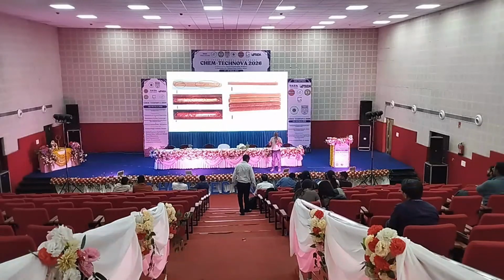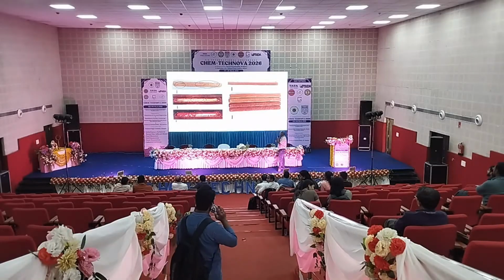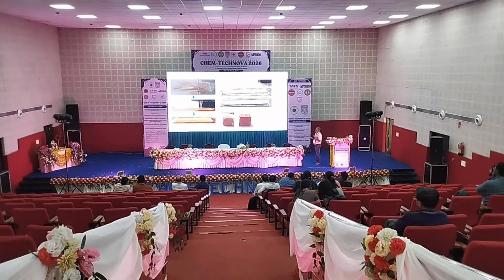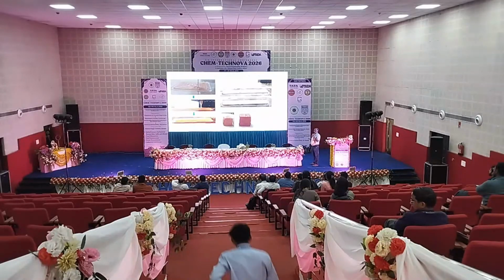What I did, I increased the bed temperature, plate temperature. First initially we tried with 40 degree, 50 degree, then I went to 80 degree. With 80 degree you can say that you have a very nice composite thermal sheet getting formed. So there are some glimpses of how the sheets are printed. At 80 degrees centigrade we could have very nice structural integrity.